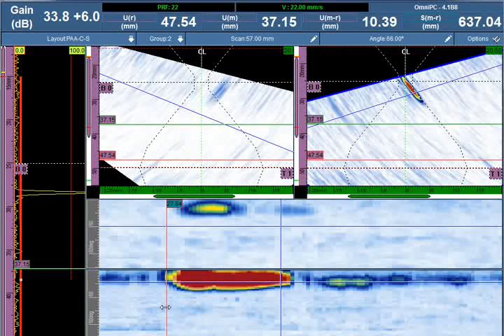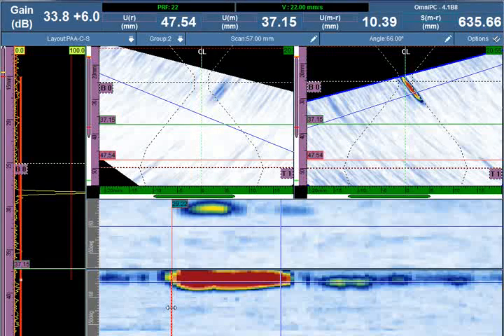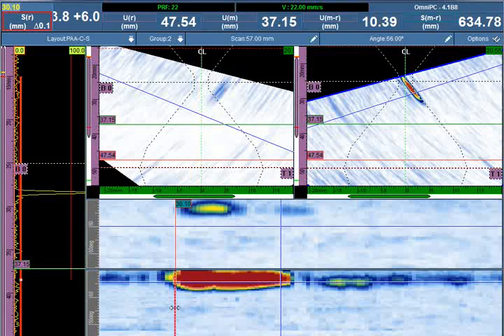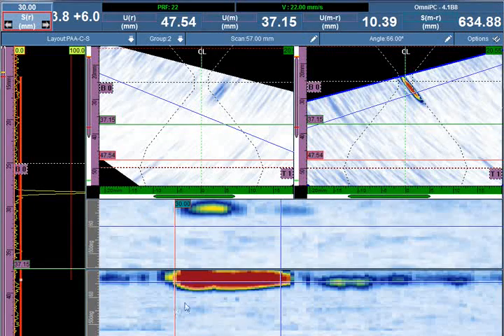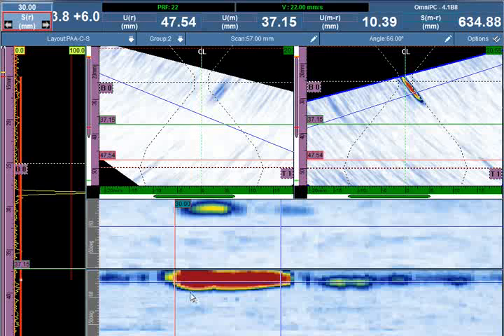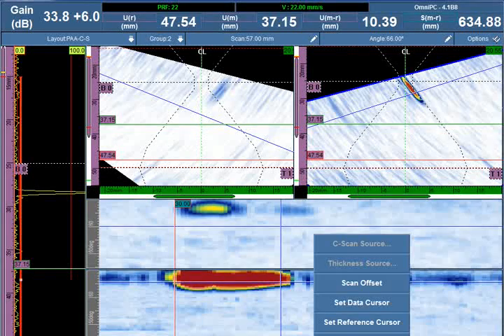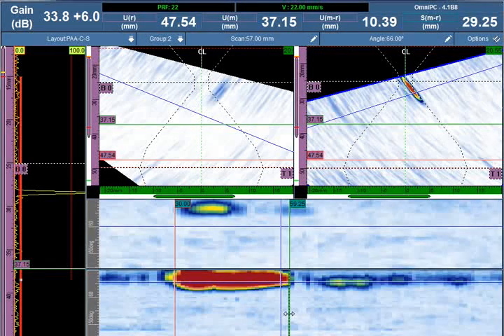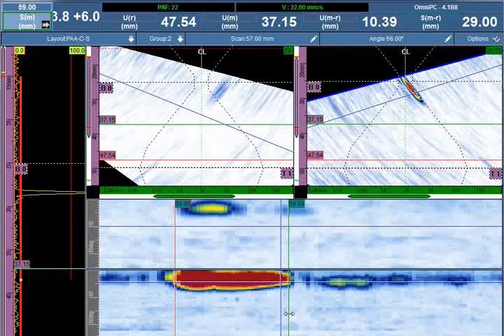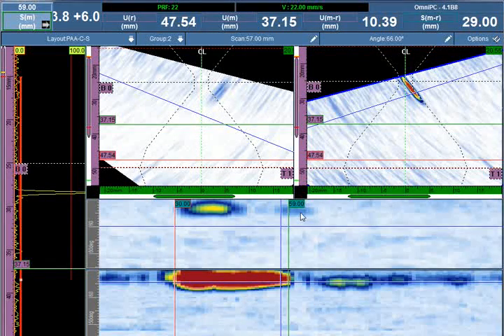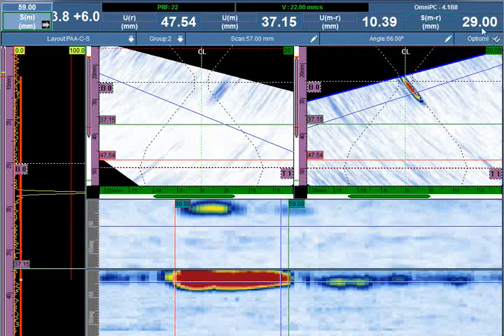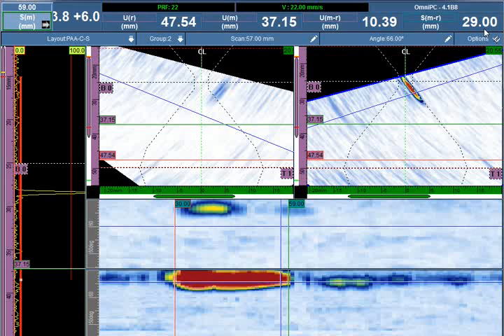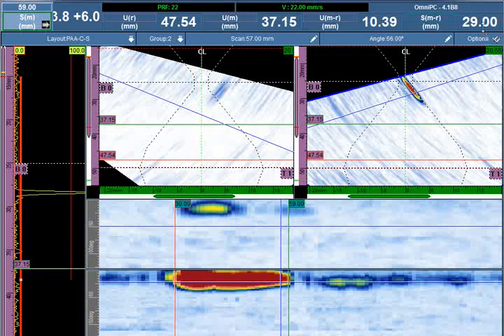The length sizing is determined on the C-scan based on the color palette representing amplitude for a 6 or 3 dB drop or a rapid drop sizing technique. In this case, we are using the color palette to visualize a 6 dB drop for a total length size of 29 millimeters.